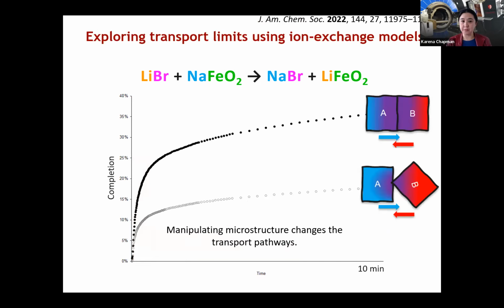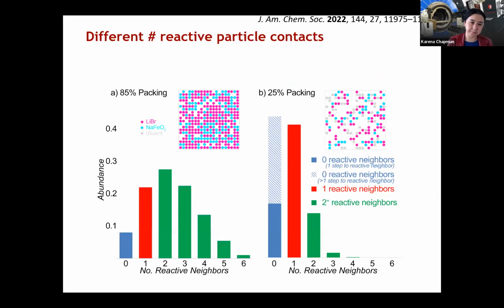Actually, what we did here was really simple: we take those same reagents and we smushed them together. So we increased the contact area between our two reagents, and effectively we decreased the transport pathways for that reaction.